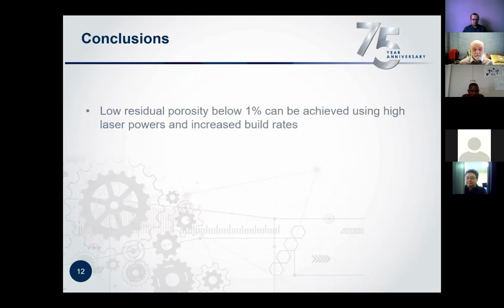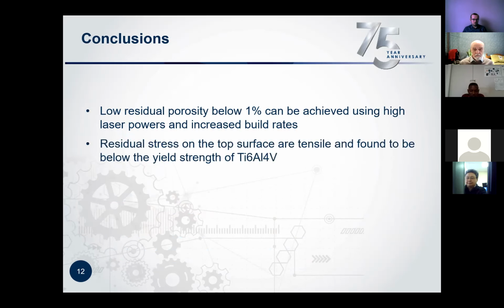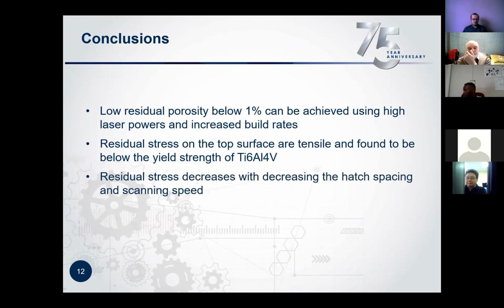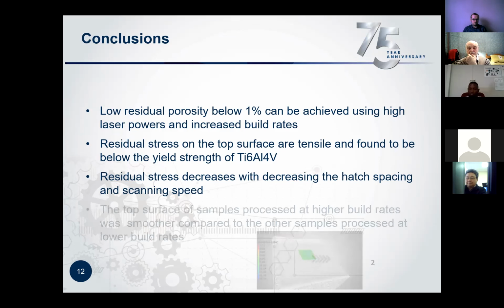So based on that, we draw some preliminary conclusions. We can see that in terms of the actual measurements, low porosity below 1% can be achieved using high laser powers and increased build rates. With the 2 kilowatt parameters, we're able to get quite low porosity levels below 1%. Residual stresses on top are tensile and found to be below the yield strength of Ti64. Residual stresses decrease with decreasing hatch spacing and scanning speed.